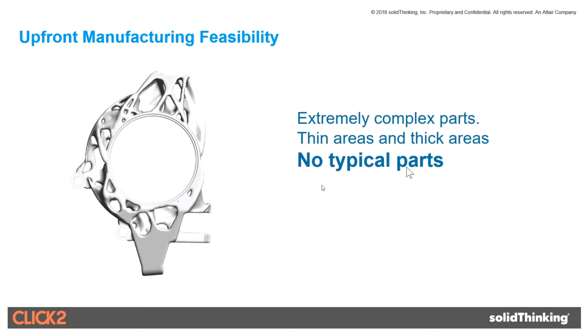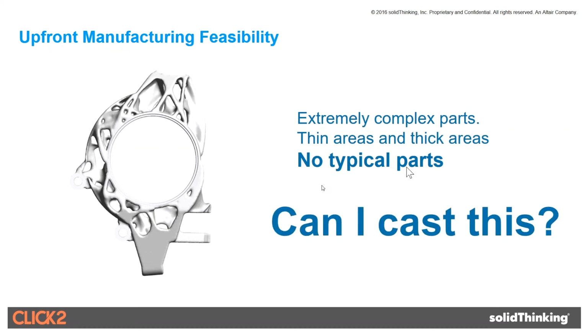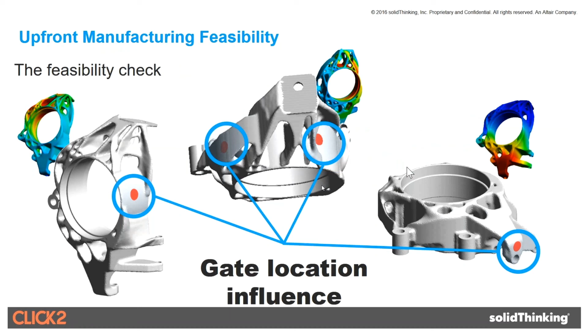contour levels, and you can see that the stress in the component is a lot lower than in the original design. We also ran a fatigue analysis on this as well, which I'm not showing here, but we also did that. In addition, we also looked at the casting, which I'll come to in a second. So basically, this is the original design, and this is the bionic structure.